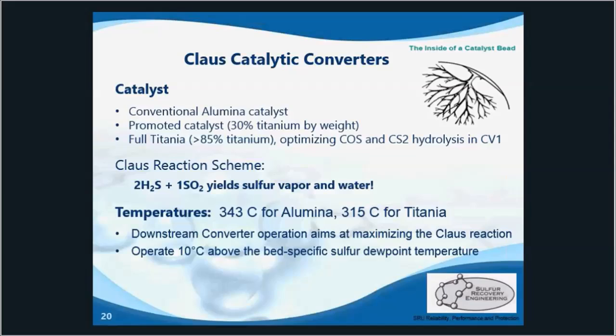Downstream converters run cooler to maximize the Claus reaction. This means operating 10 degrees centigrade above the sulfur dew point temperature, which is typically somewhere between 160 and 200 degrees Celsius. There is a picture of some nice brand new Claus catalyst that hasn't been affected by any deactivation mechanisms yet.